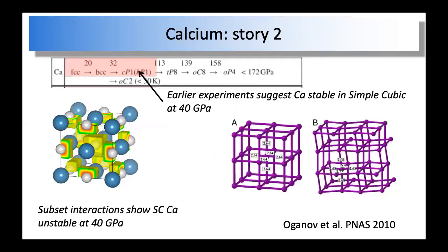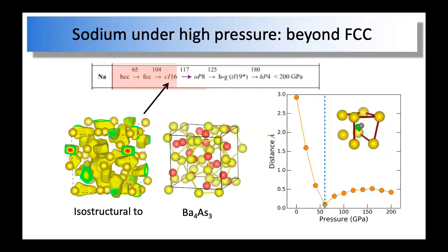And then let me skip these two things. It's just that with our theory, you can more easily explain what happened here. So another thing is why all the high symmetry structures become unstable under high enough pressure for these metals. And the reason, of course, again, is the subset repulsion. So for example, let's take sodium as an example. Under high enough pressure, like 100, 110, it becomes this structure.